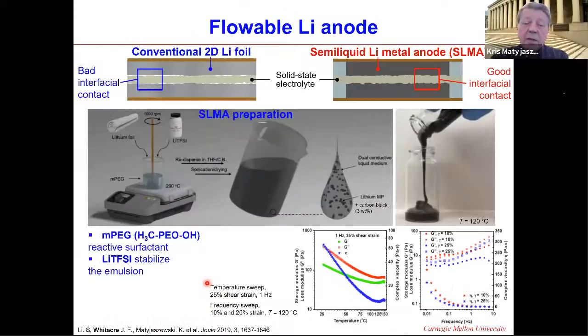So the problem is that you can use a solid electrolyte for protection, but if you are using conventional lithium metal, lithium foil, there would be a lot of empty space, and this is how these dendrites start growing. So can we use a semi-liquid metal anode? In that case, this interfacial contact would be much better.